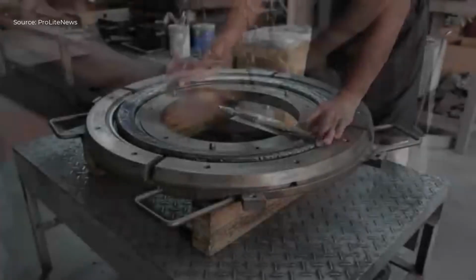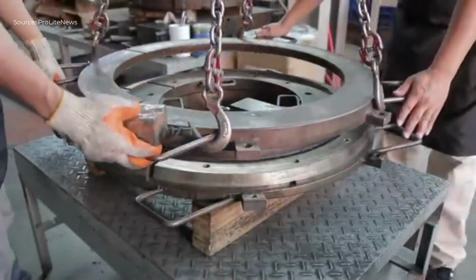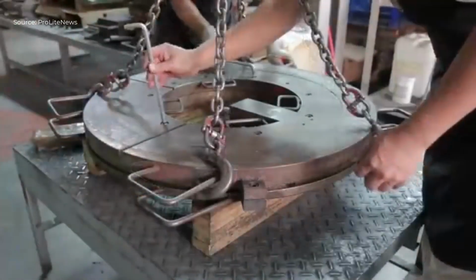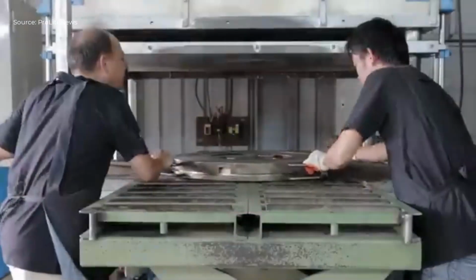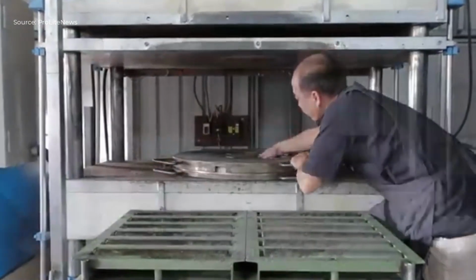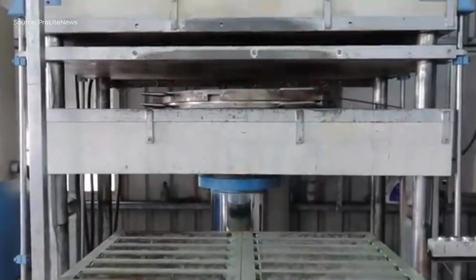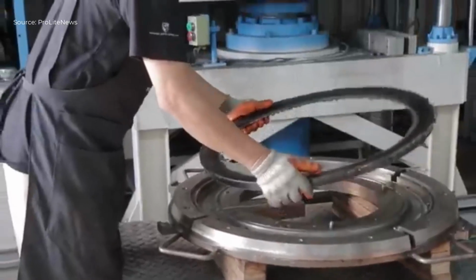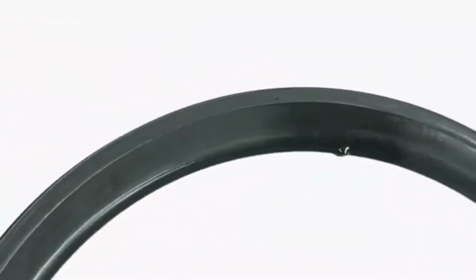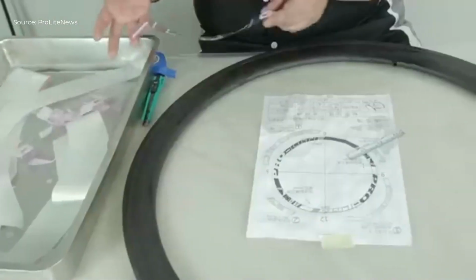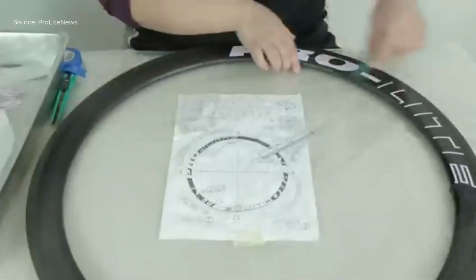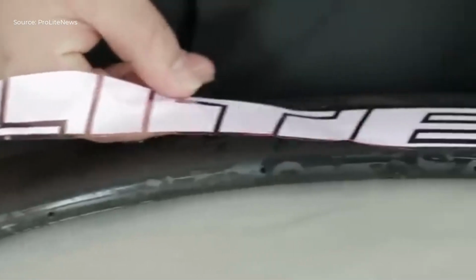Successive layers are applied to build the sidewalls and outer face of the rim. These layers are smoothed and wrapped tightly to prevent slippage before the rim is inserted into a mold. The mold is heated gradually to allow the resin to flow. Then pressure is applied in 2 stages to eliminate excess resin and ensure compact layering. Prolite uses thick-wall silicon air bladders superior to standard poly bags, which allows molding at double the typical pressure, resulting in stronger and lighter rims.